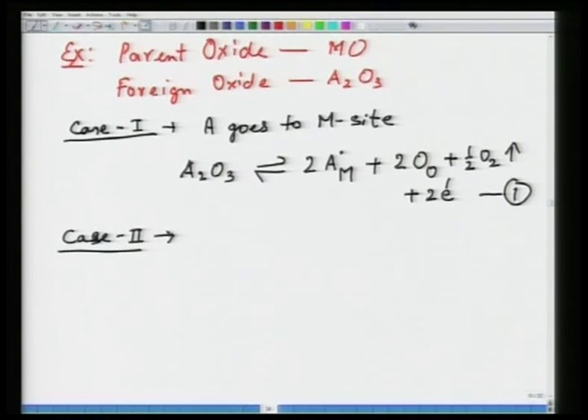Case 2. Now, here again you have A going to M site, but in this case all the 3 oxygens occupy oxygen site. So, let us see what happens here. So, A2O3. Both the A's go to M site having one positive charge at each site, plus all 3 oxygens go to oxygen site. Now, both the A's have gone to M site, all the 3 oxygens have gone to oxygen site. So, mass balance is fine, but what about the site balance?